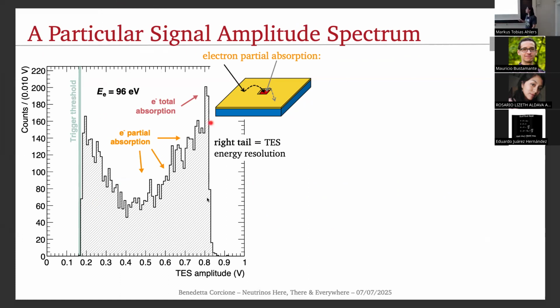Now, the interpretation of this histogram is the following. We have a full absorption peak where the electrons deposit all their energy inside the device. But this peak has two different tails. The left tail is due to partial absorption of electrons. We are using an electron source much bigger than the TES, so there are a lot of electrons bouncing nearby, and they undergo different scatterings. They may produce secondary electrons, and they end up leaving just part of their energy inside the TES, which is this tail. But the right tail of this peak is just influenced by the energy resolution of the device for electrons and the eventual non-monochromaticity of the electron source.